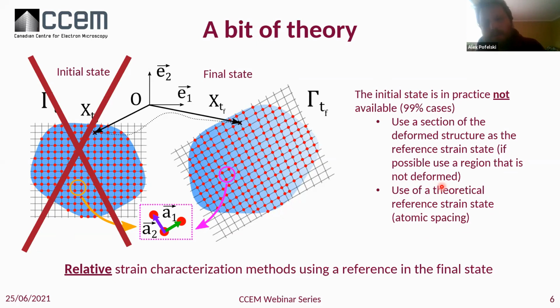The problem with using the theoretical reference is that now the calibration matters, while when you use an internal reference, the calibration doesn't matter. Often when we calibrate a microscope, your calibration standards are off by 1 or 2% regarding the level of precision. This 1-2% can be your level of strain in the material. So very often, we don't use a theoretical reference. We use a practical, experimental reference that is inside the final state. And we're going to be talking about a relative strain characterization method when you use a reference that is in the final state of deformation of your material. It's not that much of a problem because in many cases, this reference is unstrained.